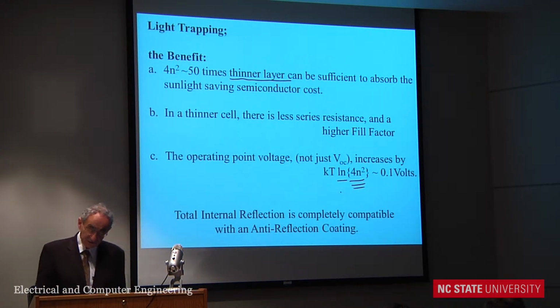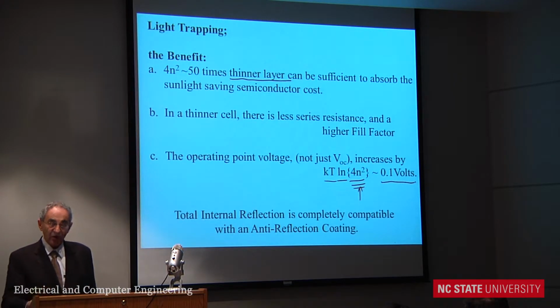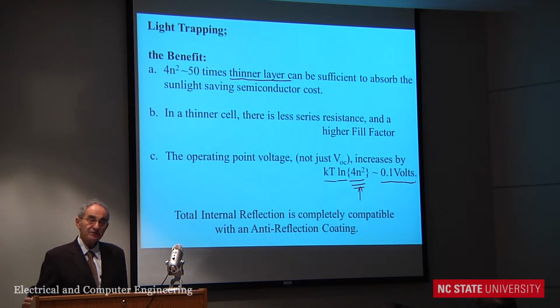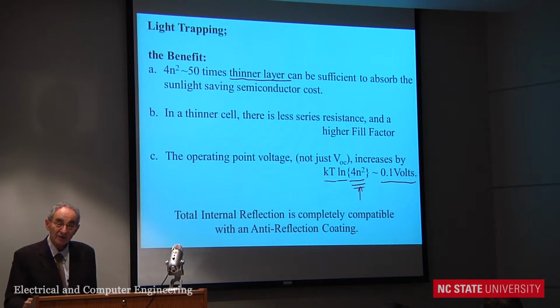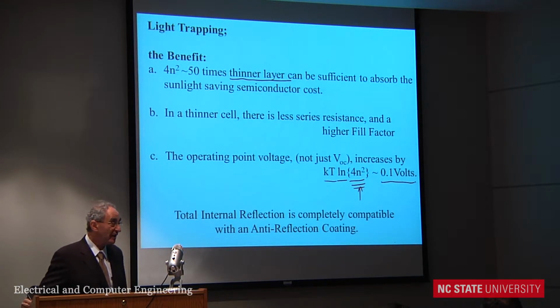And the free energy boost is kT log of that concentration ratio, which is natural log of 50, which is about 4, and 4 kT is about 1/10 of a volt. So now you're gaining current, but you're also gaining voltage. And the voltage, well, 1/10 of a volt may not seem like much, but you know all those silicon solar panels that you see out there in the fields? They're typically working at around 1/2 a volt. So if you add 1/10 of a volt, it's pretty significant.